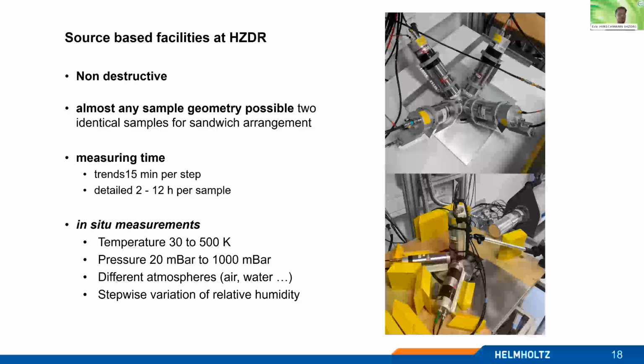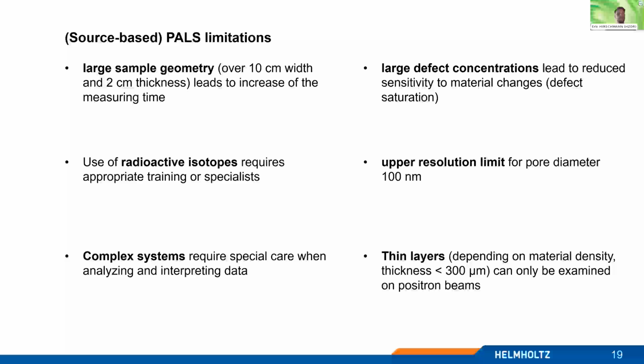And for the other one, it's also possible to vary the relative humidity stepwise using a special chamber and a kind of saturated salt to vary the humidity in situ.